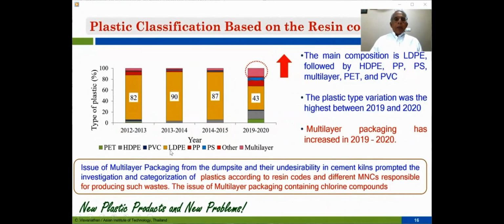This is very interesting. The LDPE contributes the largest fraction of the plastic. For example, PET and PP show very clearly that some of these things have been very well recycled. Only the components which did not have any value were not removed. And one interesting thing in recent years, if you look at it, multi-layer packaging seems to have increased. Okay, the new plastic products have created a new problem.